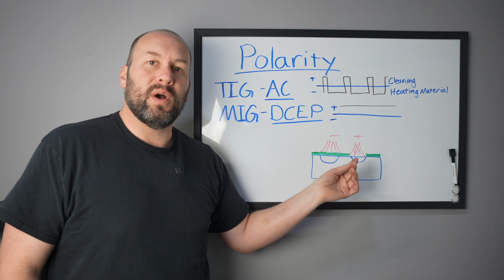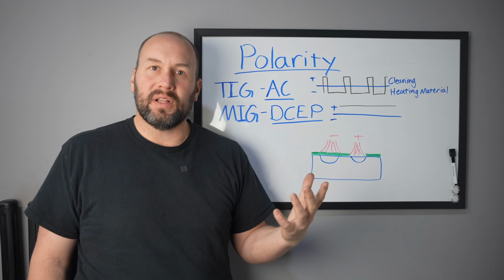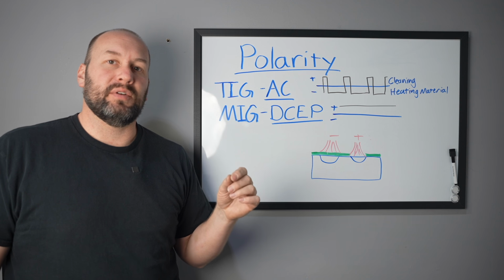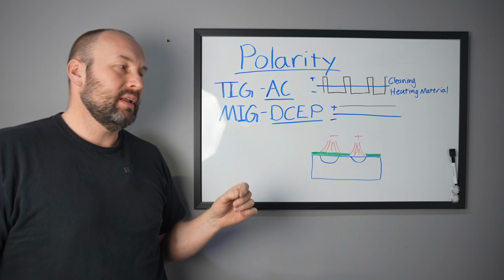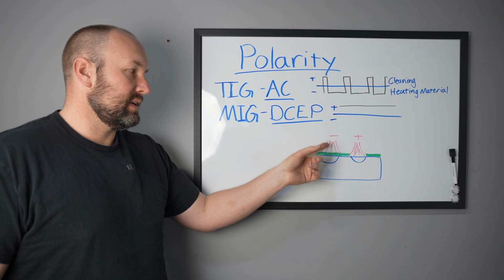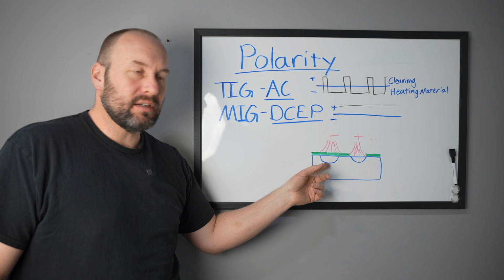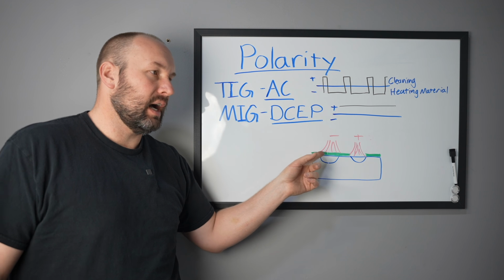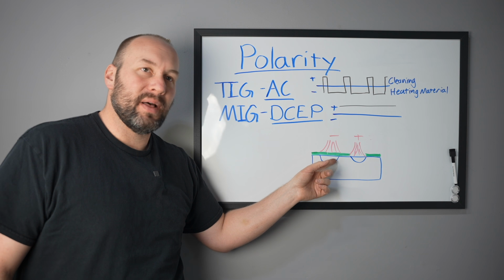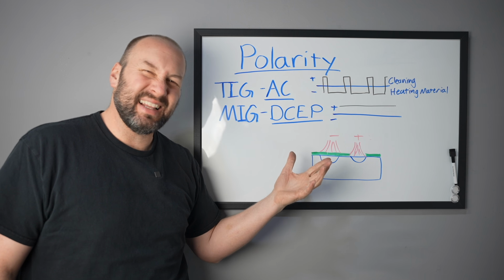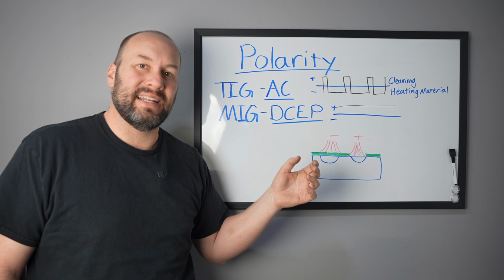But since you're MIG welding and that wire is entering the weld puddle anyway, it goes into the positive side, heats up that wire, and that wire drops into the puddle and takes the heat with it. With TIG welding, you want to put most of the heat down into the material, and so if you use electrode negative to put most of the heat down here, it won't etch the oxide layer off right here. So you'll end up melting underneath that surface. It's kind of like an M&M when the chocolate melts and the candy's still there.